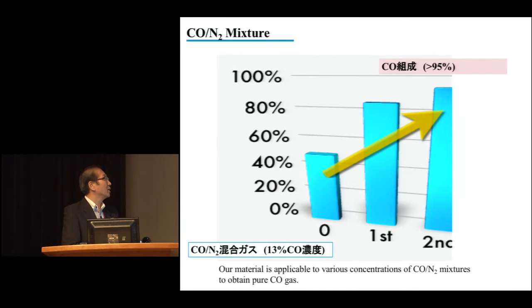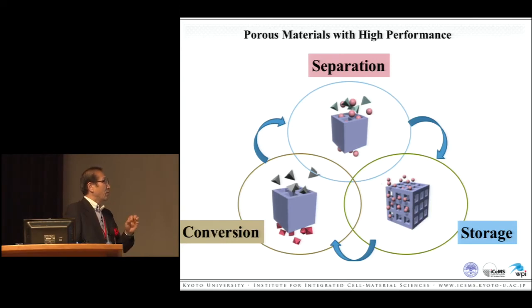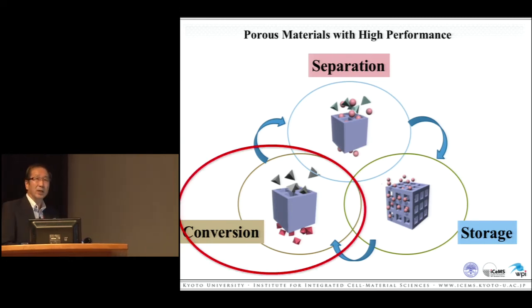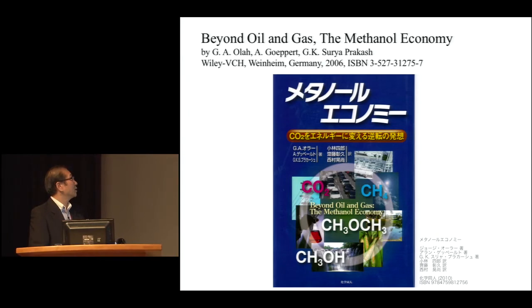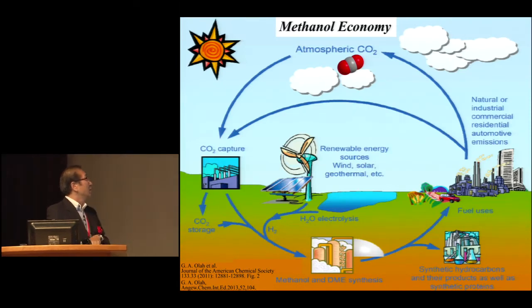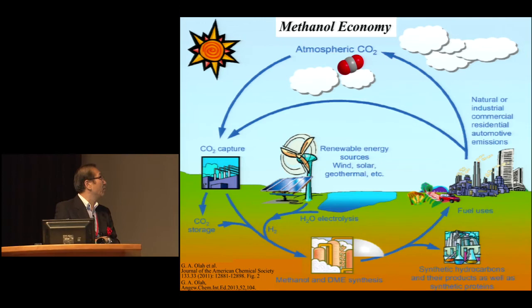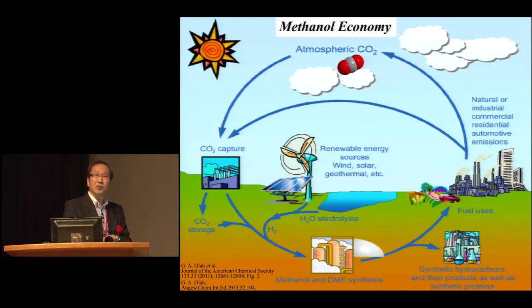Starting with 13% concentration of CO in a mixed gas, after 3 repeats, the concentration increased to more than 95%. Storage and separation are now possible. But what about conversion? We need to work more on conversion. But what is the future that can use conversion more effectively? This is by Dr. Olah, and he wrote a book titled The Methanol Economy. CO2 in the atmosphere can be taken in, using the hydrogen from the water, and renewable methanol can be generated.